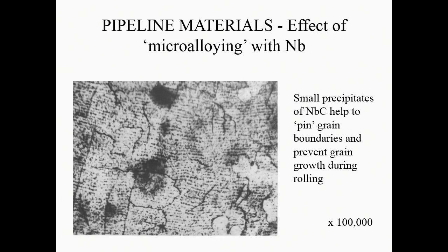Now, what niobium carbide does when it's formed: if the temperature rises, this grain wants to grow, this grain boundary has to move. It can move until it reaches these carbides, and then the carbides sit on the boundary, and for it to grow more, it has to pull away from the carbide, and that means that the carbide particles act like little nails holding the grain boundary in place. So if you've done some rolling at low temperatures or high temperatures and you don't want the grains to grow, you put these carbides in and they will prevent that grain growth from taking place.